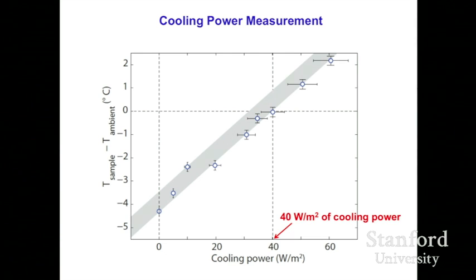So this is a proof of principle demonstration. It certainly is not the theoretical limit of the performance of these devices, and in fact we can do a lot better. So at the moment, we're trying to further improve upon this, as well as to scale this up. At the moment, we have an 8-inch wafer, and we're trying to scale this up into enough area to cover some part of the roof to demonstrate actually an air conditioning system.